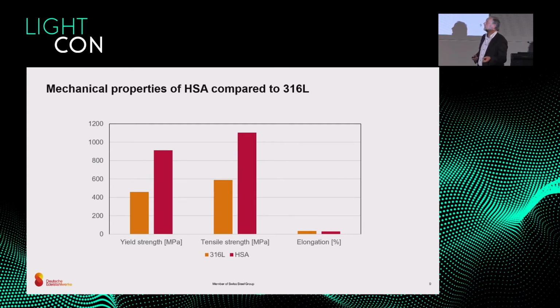We increased the yield strength, what's important for construction, nearly by a factor of 2, and tensile strength the same. For the higher strengths, you have to pay for less elongation or ductility, but the steel is still, due to the austenitic structure, very ductile, and you have a high toughness.